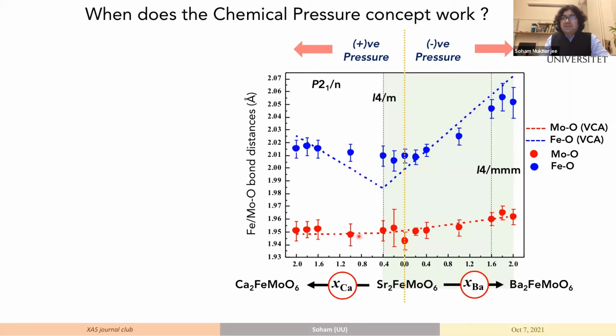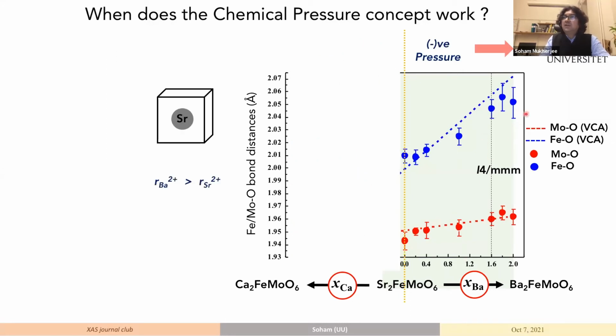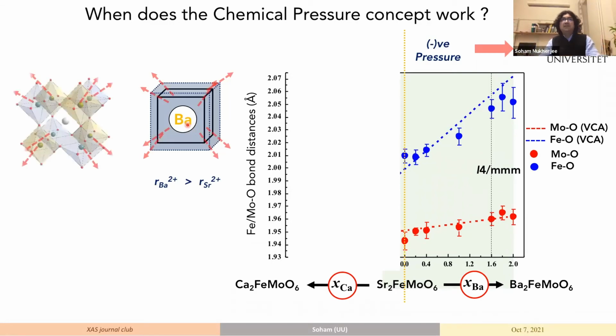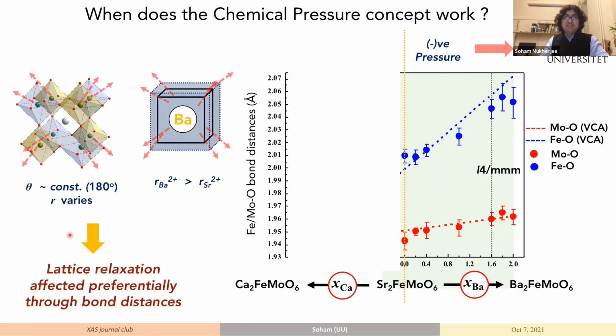We go back to the master plot, and we now focus only on the negative pressure side. We remember here that the bond angles are not changing too much. They are very close to 180 degrees. So when you try to put in a bigger ion, the angles are already at the maximum values. So only the distance can change, and lattice relaxation is then affected preferentially through bond distances, and hence it scales roughly in according to the